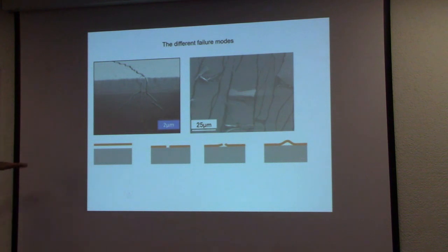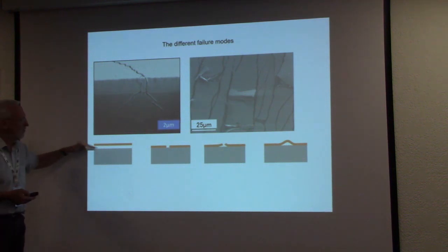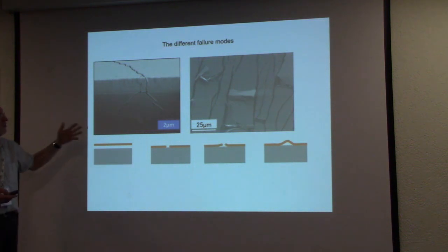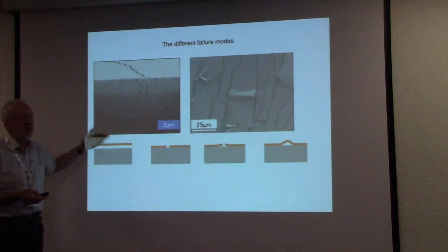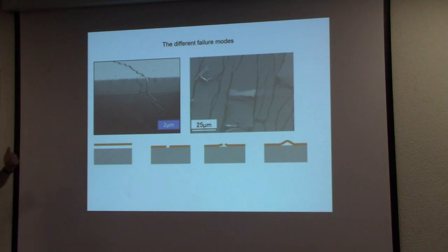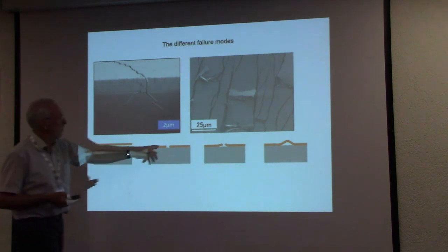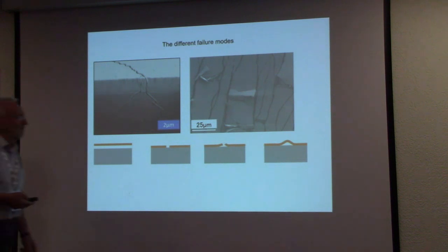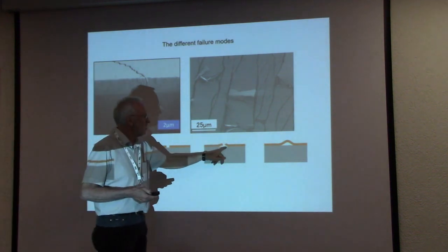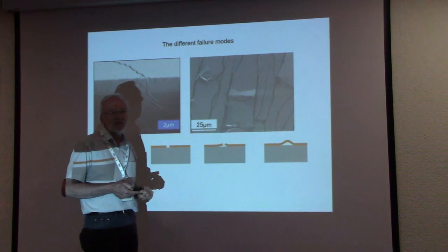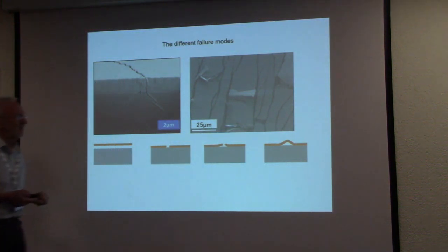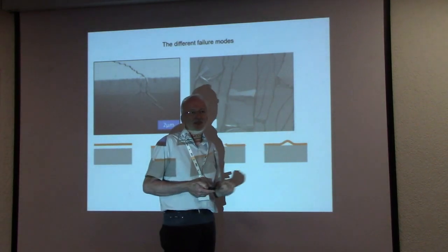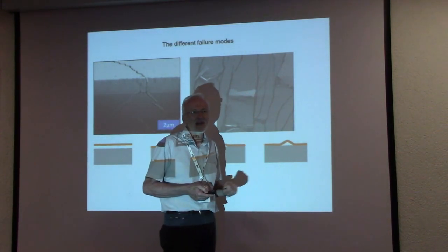So one of the things what may happen, it is a complete spoiling up of the film, for example. Even when we look to the most simple case, only a film on a substrate. Yes? Then the film may fracture. Then the film may fracture and decohesion may take place, yes, at the interface. Or we will have only a decohesion, yes, such a buckling.